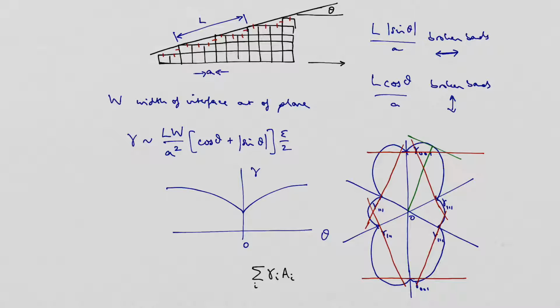In fact, the 100 surfaces of sodium chloride are so much lower in energy than anything else that you end up with cubic crystals. You can see those. There are other ones where the form of the crystal reflects the form of this construction. But there are others, if the crystals have formed far away from equilibrium, where this is not relevant, because this is just around thermodynamics. So sometimes it helps you understand what's going on, but not always.